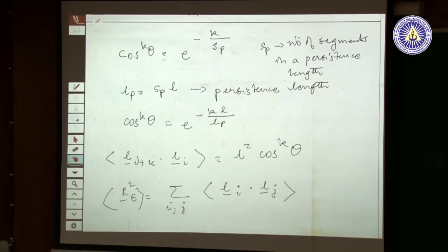But as you go further and further away, there is this idea of the persistence length Lp, and you can calculate it because we saw how Sp was defined as 1 over log cos theta. So you know cos theta for your system, what Sp is, and therefore what Lp is. DNA has a certain persistence length because it has a local rigidity. For DNA we are interested in knowing how far along the backbone you have to go before it becomes flexible. So persistence length is the distance along the chain where it gets uncorrelated. Yeah, exactly, distance along.